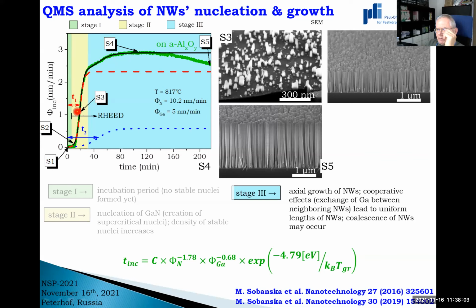An important part of this work is that we measured how this incubation time changes with nitrogen flux, gallium flux, and surface temperature. This is important if you want to control the process. You need to know how the system reacts to the fluxes and surface temperature.